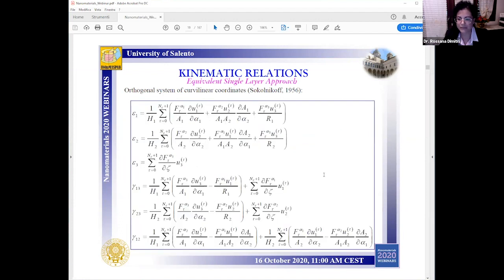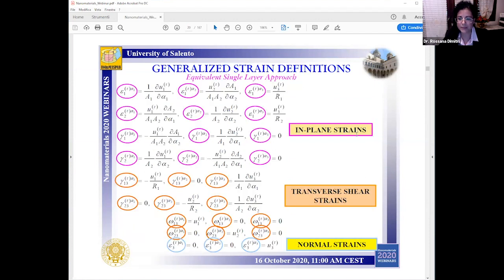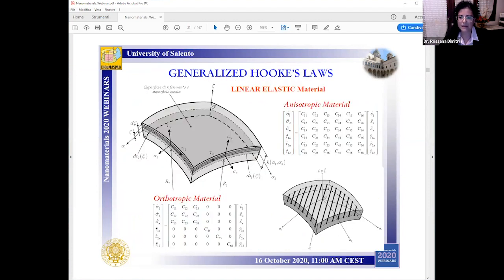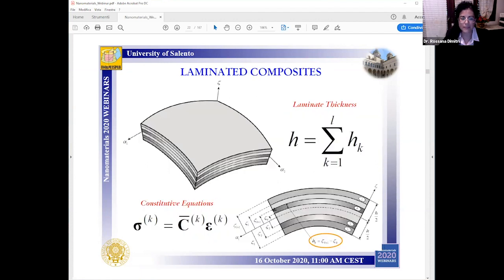So here, as you can see, within an equivalent single layer approach, the following definitions are set for the in-plane strain components, the transverse shear strain, and the normal strain components. An important aspect now is related to the design material, its mechanical properties, the constitutive law, and under a linear elastic material assumption, for example, see the constitutive law introduced for an anisotropic material with the well-known 21 elastic constants, or the orthotropic material with the 9 constants, or once again, the laminated composites with a fixed number of